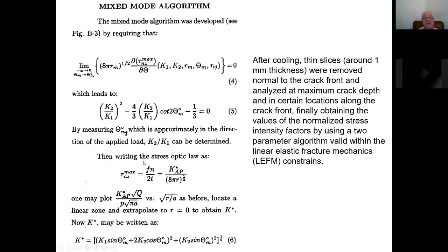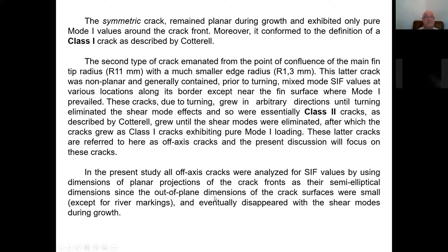This is the square root of the elliptic integral because, assumably, you had the initial crack as an ellipse. And then this parameter can be used if you have the mixed mode. Now, what was noticed? Well, we had essentially two types of cracks, as Cottrell named it. Class one means essentially mode one. So this can be a symmetric crack, or this can be an off-axis crack, which grew by eliminating mode, shearing modes. We're going to see this further.